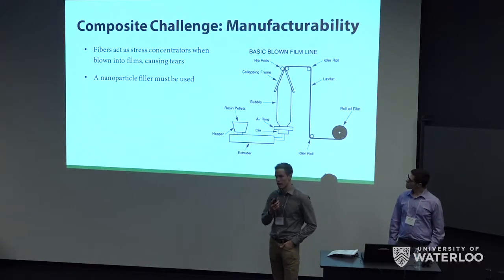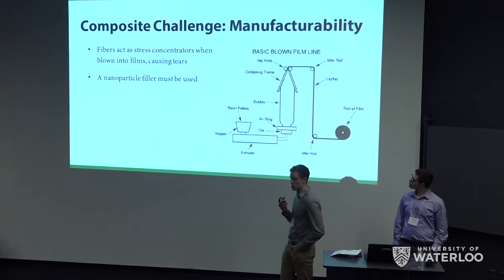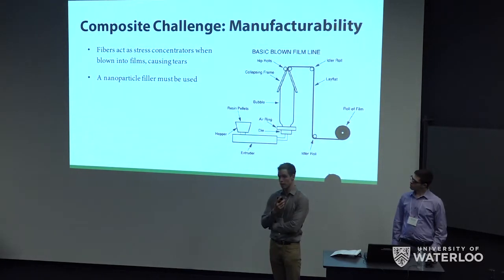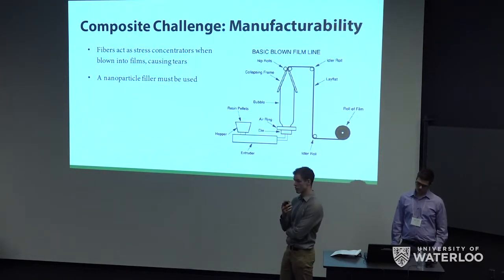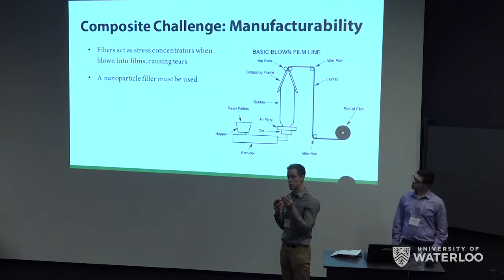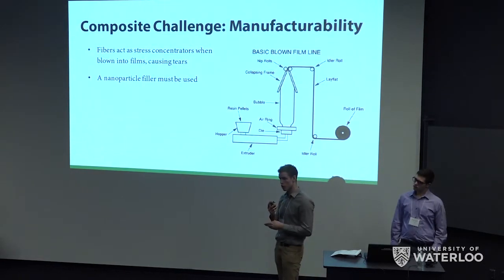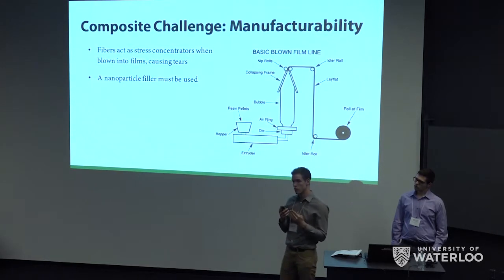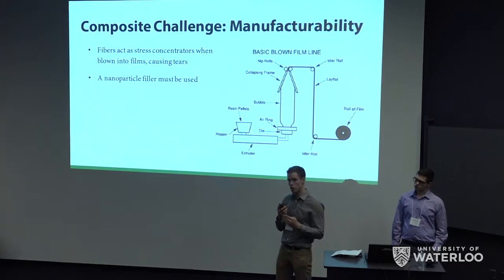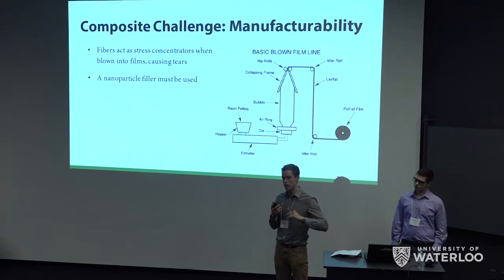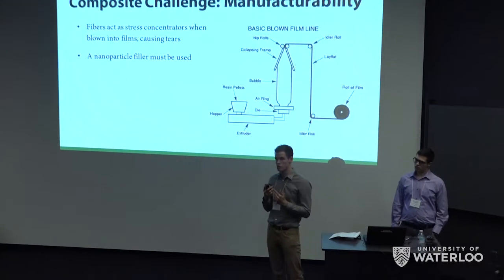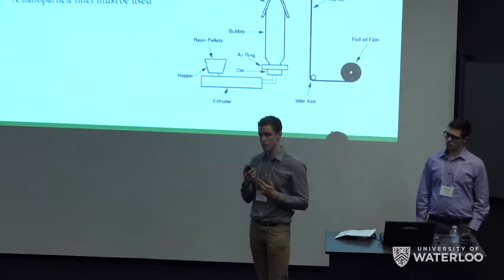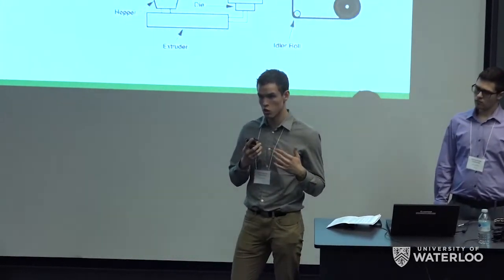barrier properties of bags. So essentially all plastic bags produced today are created on a film blowing line. So this involves melting the plastic, blowing it into a bubble, and then collecting it onto a roll. The problem here is if you have fibers inside of the matrix, these do not elongate and stretch as the plastic is being blown into the bubble and concentrate stress at the ends and lead to tears. So these cannot be manufactured, so this is not a viable option.